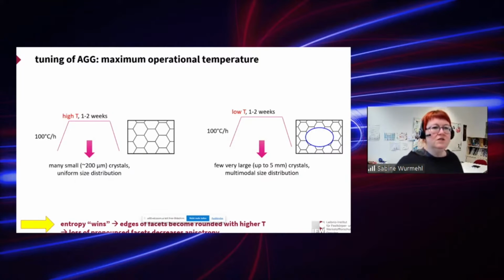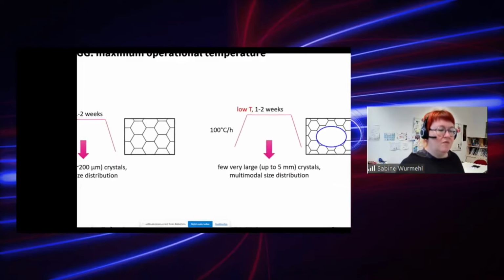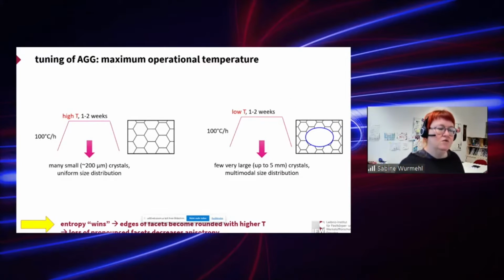But you also need to find the optimal window where you have the anisotropic abnormal grain growth, because if you are too high in temperature, you have too much entropy and the facets of your grains become rounded. These pronounced facets are very important for your anisotropy, so if you go too high, you get back to normal grain growth. But you need high enough temperature to allow for diffusion-controlled processes, yet low enough to hinder entropy around the facets.